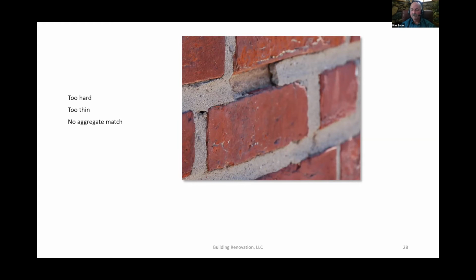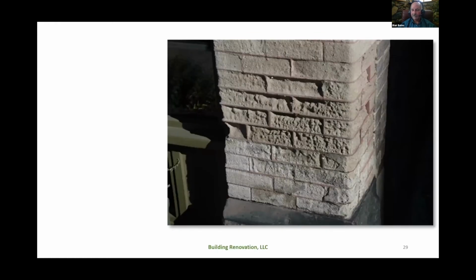Not sure what that is, but it came from Chicago. We do know what a Chicago common brick is, but it's a soft brick. Each brick will absorb about 10 ounces of water to fully saturate it. If it rains and this brick gets wet, it goes down into the mortar. If the mortar then can't pass it back out along with the brick evaporating it, then it freezes behind it and pops it off, and this is what you get. So they paid to have this entire building tuck pointed, and now they have to pay to have the tuck pointing removed when they didn't need to do 100%. But they need to have it removed and done properly, or the building will start failing much worse than it is right now. Now this is a pilaster, a column base, and you can see the mortar is great.